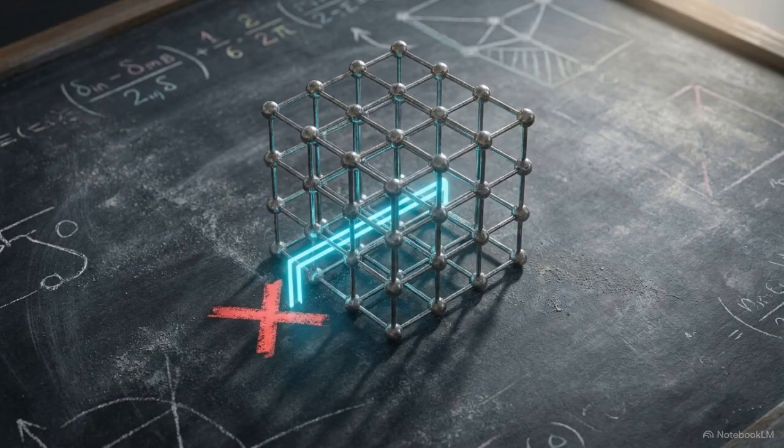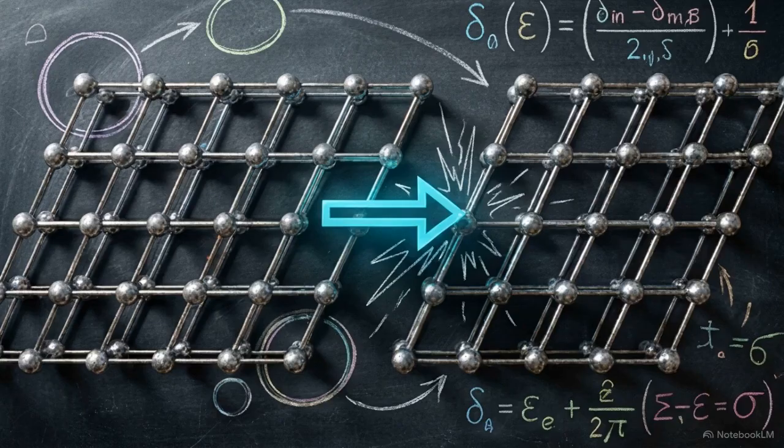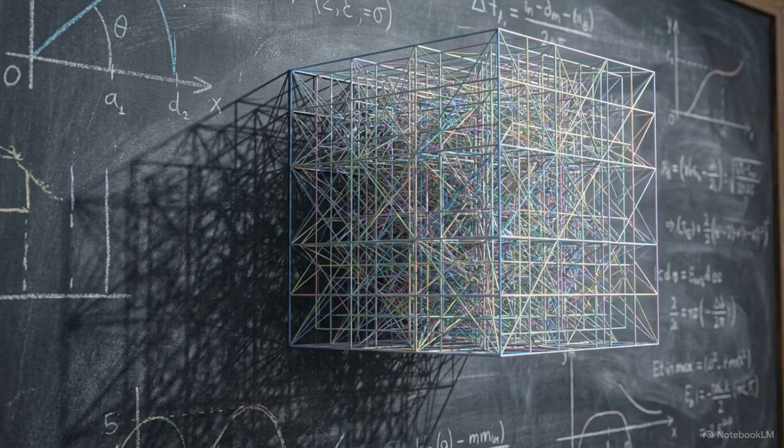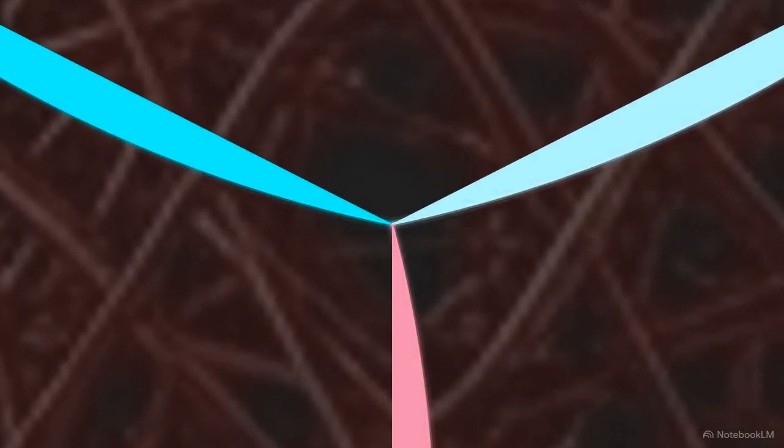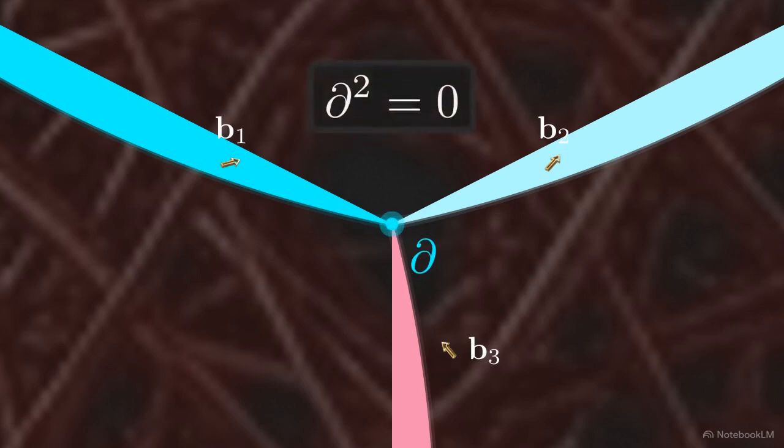This imposes a rigid structural constraint. An isolated dislocation line cannot terminate freely in the middle of a perfect bulk crystal. The topological charge has nowhere to dissipate. To analyze networks where millions of these constrained lines intersect, researchers rely on geometric measure theory. In this mathematical framework, isolated dislocation lines are represented as de Rham currents. Each current carries a specific coefficient drawn directly from the crystal's lattice group. When these currents intersect at a node, we apply the boundary operator from differential topology.